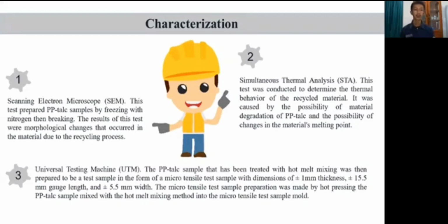Characterization. 1. Scanning electron microscope or SEM. This test prepares PP talc samples by freezing with nitrogen before breaking. The results of this test were morphological changes that occurred in the material due to the recycling process. 2. Simultaneous thermal analysis or STA. This test was conducted to determine the thermal behavior of the recycled material. It was caused by the possibility of material degradation of PP talc and the possibility of change in the material melting point. And 3. Universal Testing Machine or UTM.